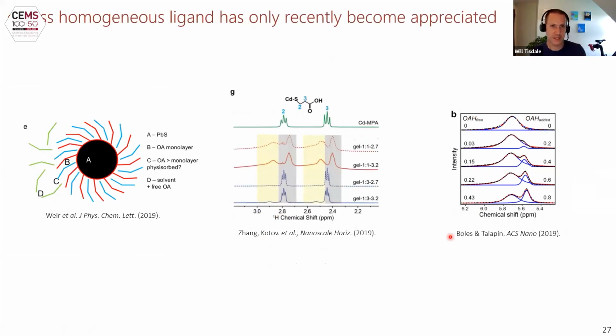The effect of excess homogeneous ligand is a very recent realization. All these papers are from 2019 here. This is work from Mike Weir's group at Sheffield, where they did some neutron scattering experiments and concluded that some free ligand in solution is associated with, or physisorbed, as they said, to the ligand shell surrounding the nanocrystal. This is work from Nick Kotov's group and Dmitry Talapin's group.